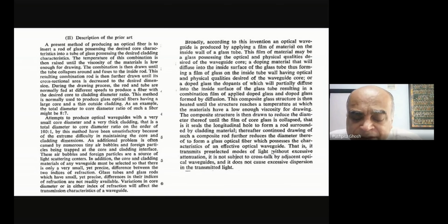So you can also imagine that depending on the thickness of the film which you are using, I can have different core diameters, because it is that film which is collapsing into a rod. So the thicker I make the film, the thicker will be my rod. The thinner I make the film, the thinner will be the rod. Is that clear to everyone?